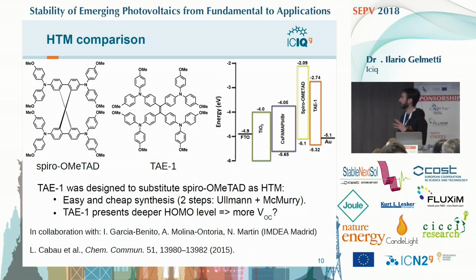Okay, so for having some insight into what's happening there, we try to change as little as possible. So we changed just the HTM, keeping everything else the same, trying to have the same thickness of the hole transporting material. So we obtained this TAE1 from Nazario Martin's group in Madrid, which is basically a very similar structure to spiro-OMeTAD, but has a different core. This makes it easier to synthesize and cheaper. We were also interested in it because it showed from cyclic voltammetry a deeper HOMO level. So we thought, deeper HOMO level, we can obtain higher open circuit voltage. Could be interesting to try.